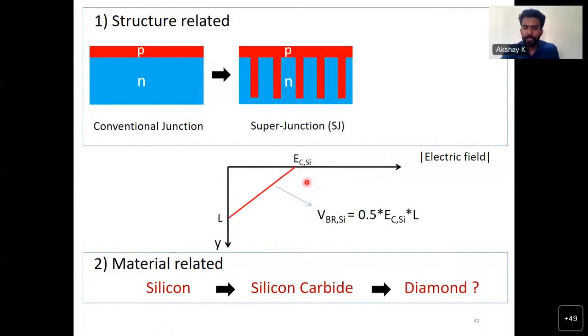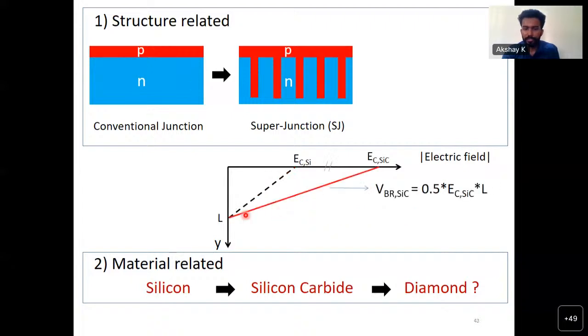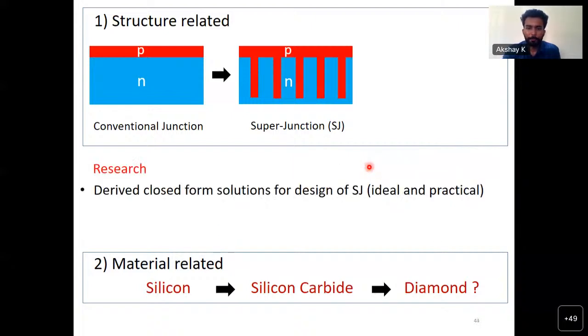Let's look at it. Here is the breakdown field distribution of a silicon PN junction diode. If you simply replace the material, imagine this is the junction. So if you make this using silicon, this is the breakdown field distribution. Now you simply change the material to silicon carbide without changing any other parameter. What happens is you will end up having a much higher critical electric field, because silicon carbide can withstand much higher field, almost 10 times the field of silicon. So that's how it's able to achieve larger breakdown voltage.